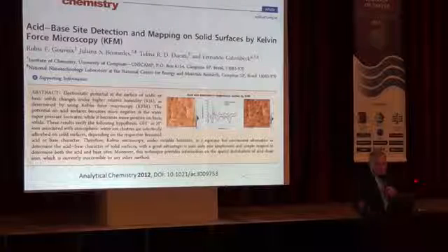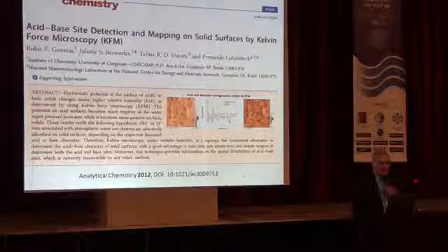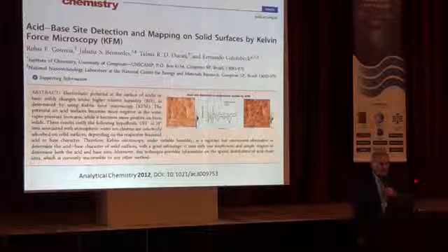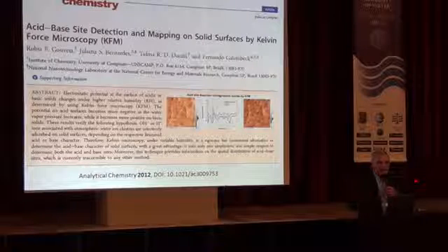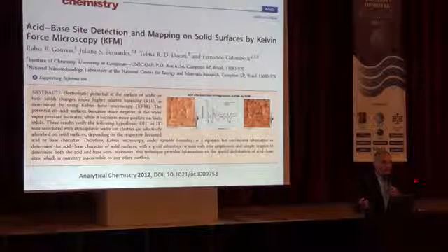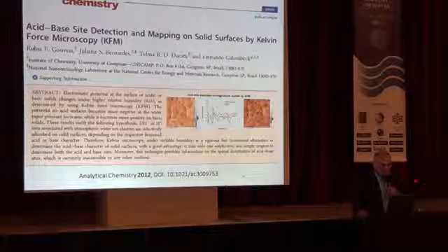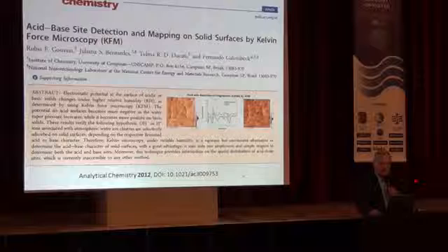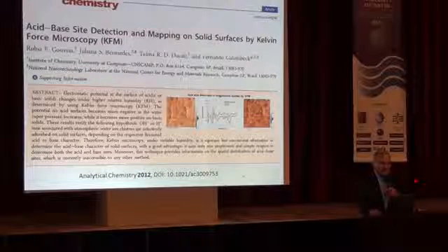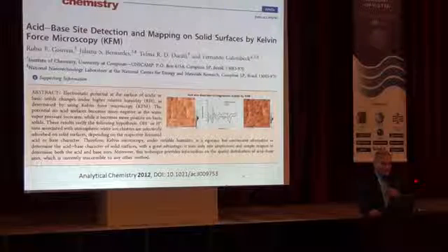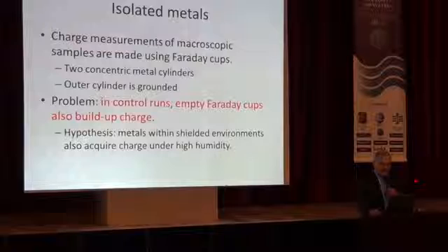And using this, at the end of last year, we published this paper showing a very useful chemical application. We can detect acid-base sites on solid surfaces, which is very important for characterizing catalysts and adsorbents, by using Kelvin force microscopy. And the only reagent to do these determinations is water, which, by the way, is amphoteric.